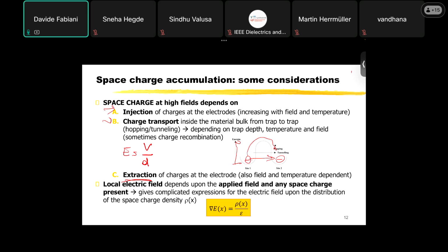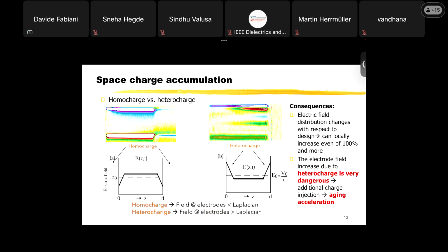And the situation is more complicated because we need to take into account the local charge density. We can have a field that is increased or decreased depending on the kind of charge that we have. In particular, we can have homocharge or heterocharge. Homocharge is the charge, you can see here a space charge pattern where this is the thickness of the material and this is the time of the voltage that is applied. So you can see that this is negative charge, this is positive. We see that we have accumulation here of negative charge close to the negative electrode. This is a homocharge. As here, we can see positive charge accumulating close to the positive electrode.